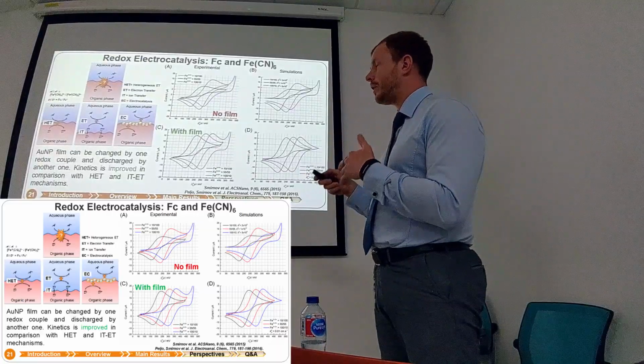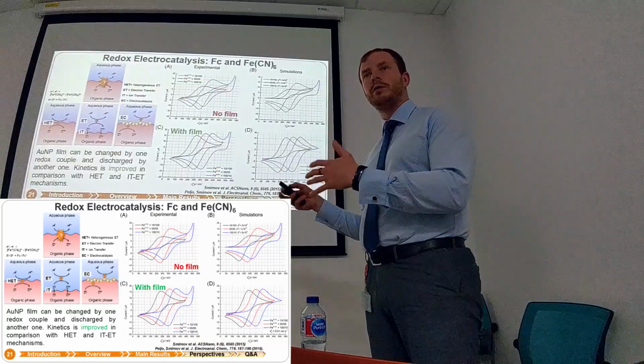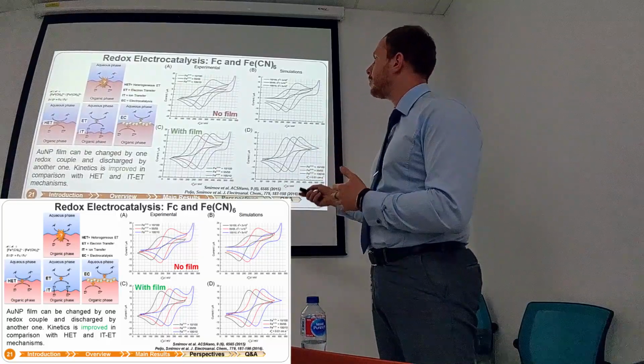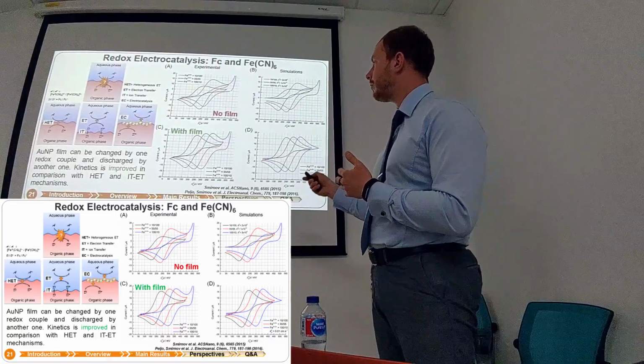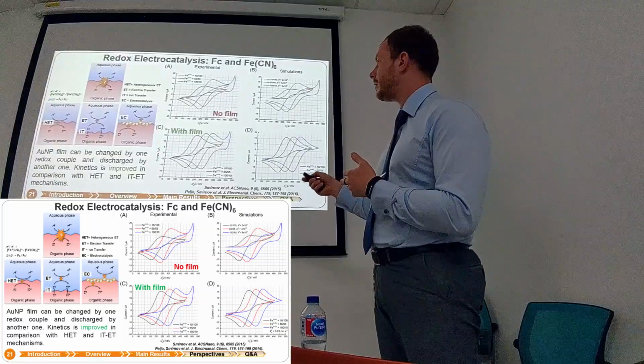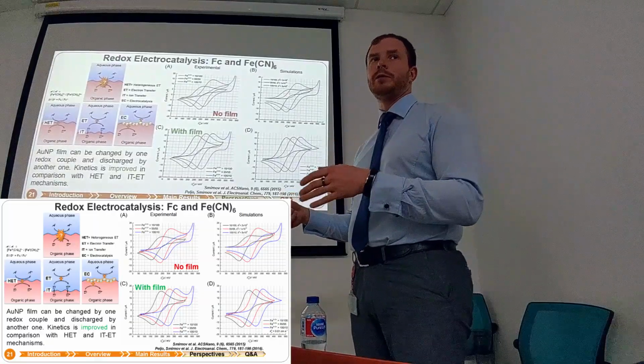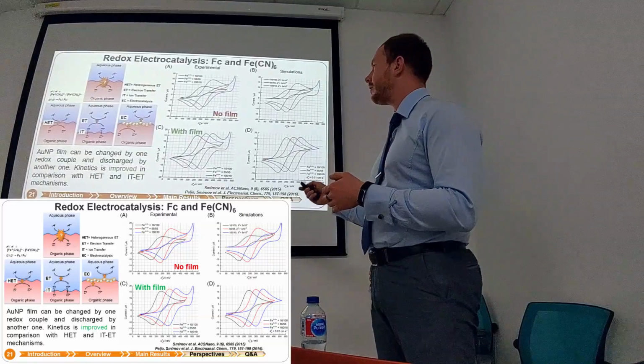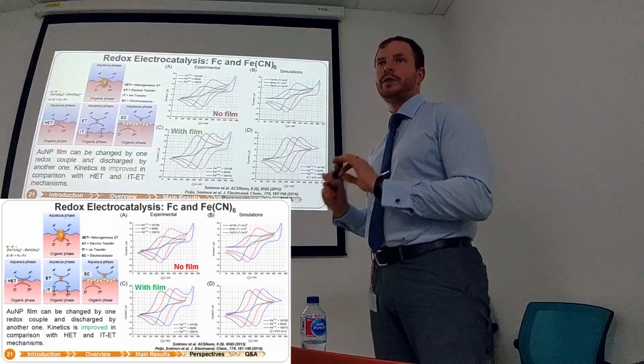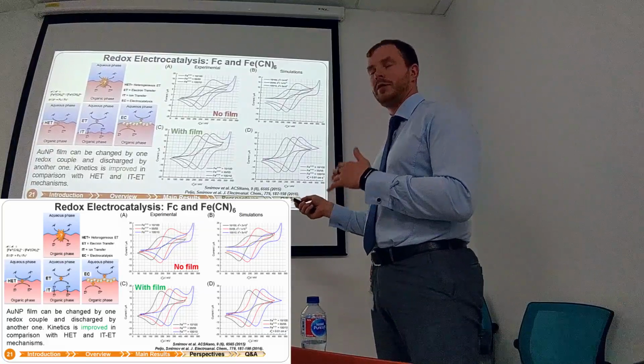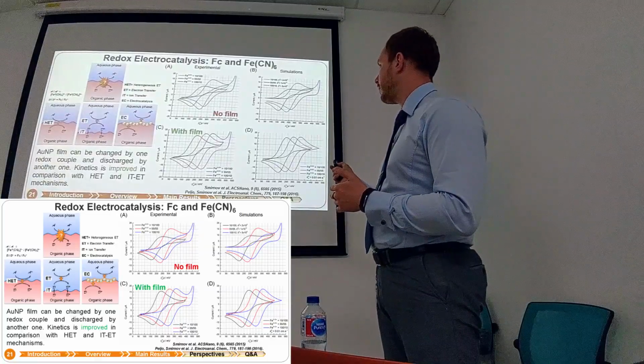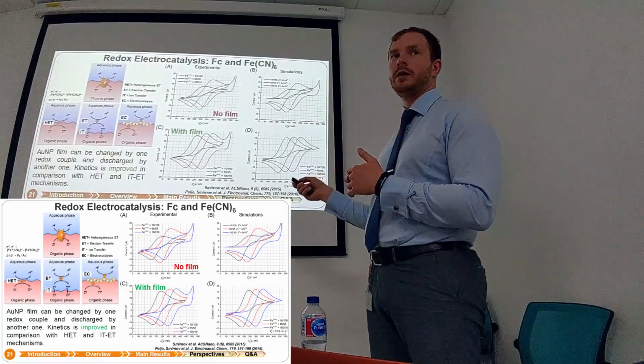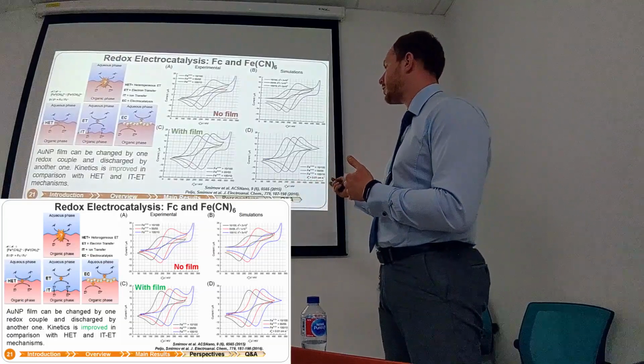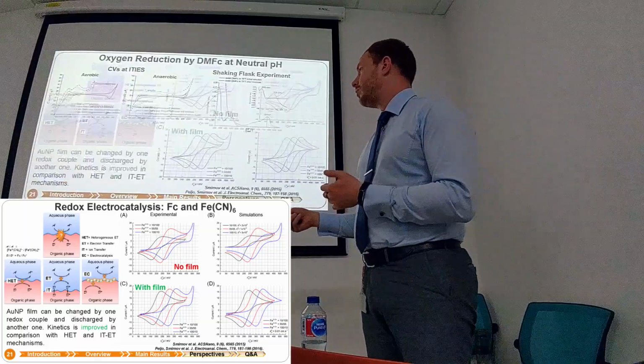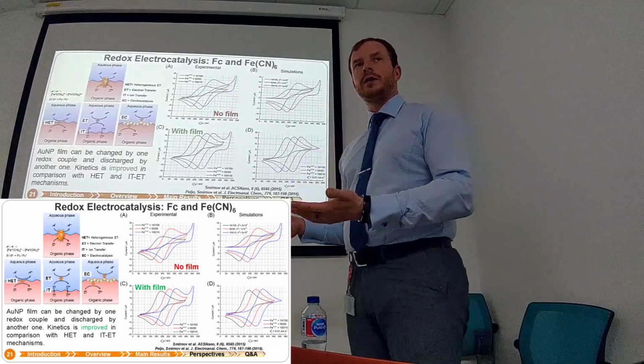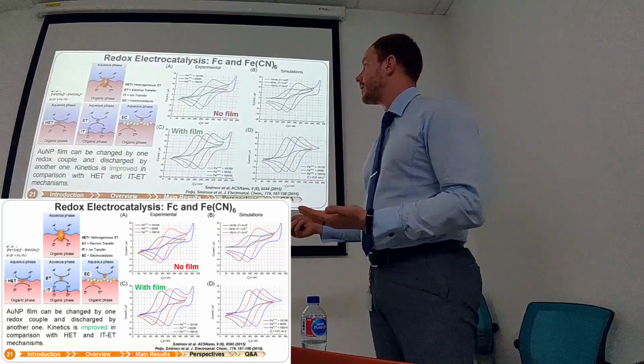So we call it redox electrocatalysis, and I don't want to speak much about that because it's too boring. Just to show you these experimental curves. There is no film. There is a film. You can see that here there are some problems with the CV. For people who have been doing electrochemistry for a while, this CV looks ugly, but this CV looks just fantastic. It's just like from a textbook. And if we are talking about simulations, we can't simulate these CVs properly, but those CVs we can simulate amazingly well. So gold nanoparticles also improve the kinetics of all the reactions happening at the liquid-liquid interface.